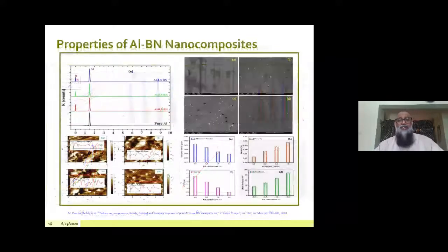The third composition we have developed is aluminum boron nitride nanocomposites, and various compositions were developed. We can also see that the strength and the hardness are increased with the increasing content of boron nitride, and the thermal coefficient is also going to decrease with the increasing boron nitride content in the composite.